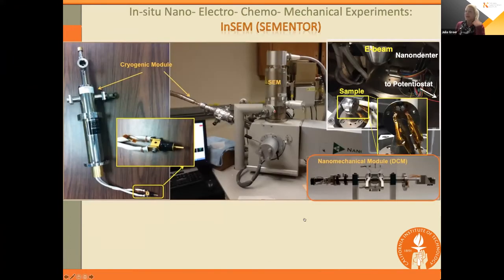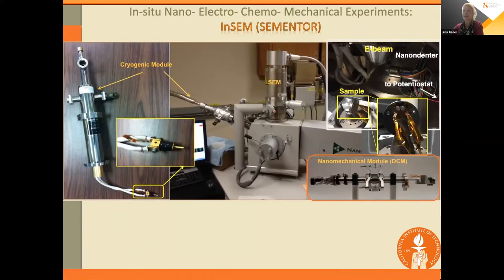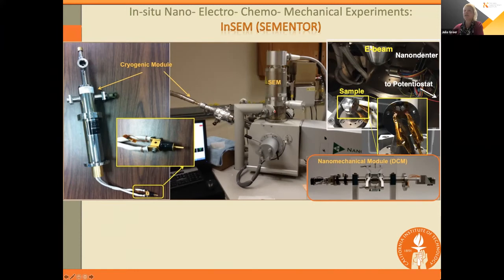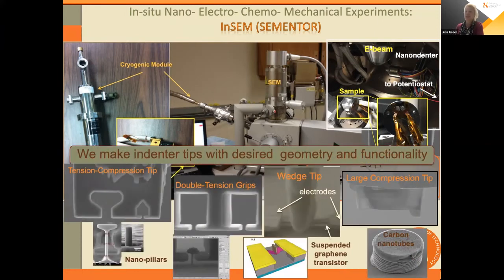Now, everything we make is nano-sized or at least micro-sized, and so its deformation can't be easily observable just by optical methods. So we have a special instrument that is effectively based on the scanning electron microscope. So here you see an SEM chamber, and it's equipped with various whistles and bells like the nanomechanical module and cryogenic module, as well as electrochemical cell. And these are the so-called different in situ devices.